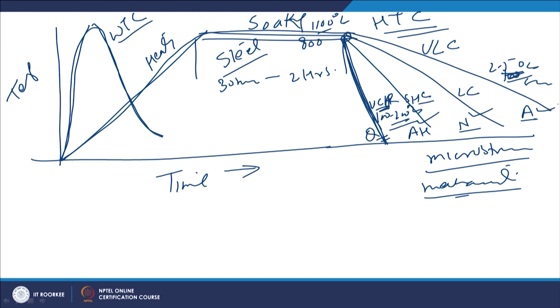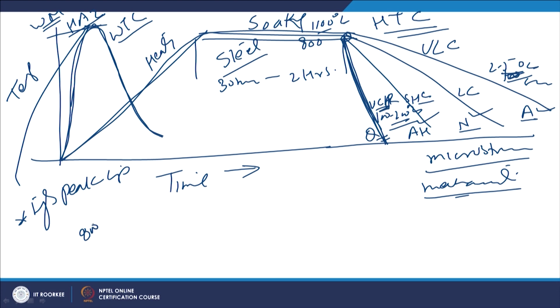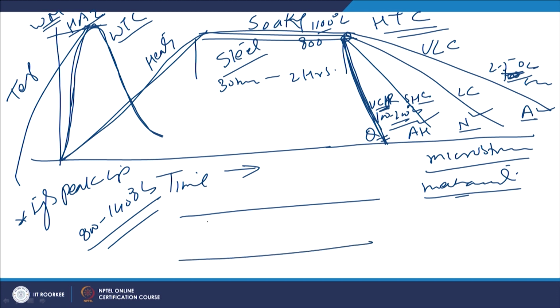On the other hand, if we see the weld thermal cycle of the heat affected zone or of the weld metal region, it experiences the higher peak temperature, which is of importance, like say 800 to almost up to the melting point, say in case of steel 1400 degree centigrade. So, this temperature will be changing. Next to the fusion boundary, it will correspond to the fusion point, or the melting point 1539 for typical pure iron, and the lower values for the steels.